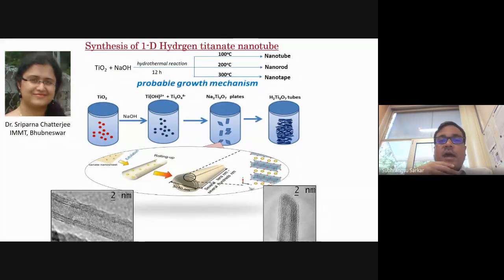She prepared hydrogen titanate nanotubes as well as titanium dioxide nanorods in a chemical process called hydrothermal synthesis. So basically, one has to take titanium dioxide, put them in sodium hydroxide, and heat them at different temperatures to reach different kinds of nanostructured shapes. Like at 100 degrees centigrade, you will reach nanotubes, which have a hollow inside. At about 300 degrees centigrade, you reach nanotapes. Now, what is important to understand is that by changing the shape of these nanostructures, we change the effective surface area or the surface to volume ratio of the system. Now, as explained before, the surface is extremely important when it comes to reactions.